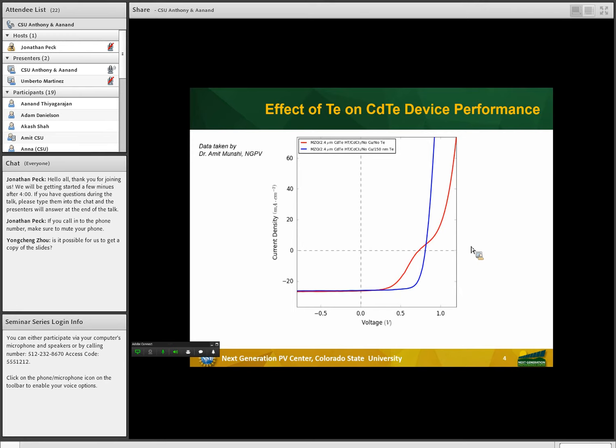The JV curve shown here shows the effect of tellurium on the device performance. This data was taken by Dr. Amit Munshi at our NGPV Center. And as you can see in the red curve, the solar cell device without tellurium shows a kink present in the JV curve, mainly due to inefficient hole carrier collection at the back of the CdTe device.